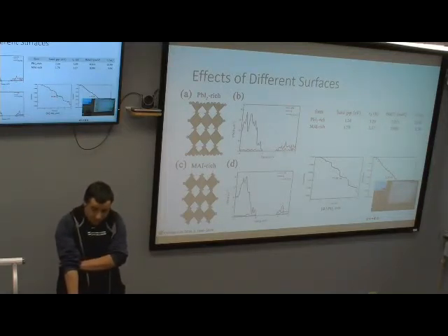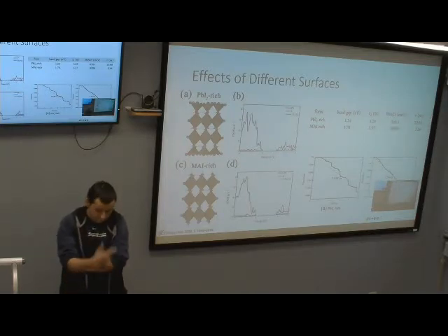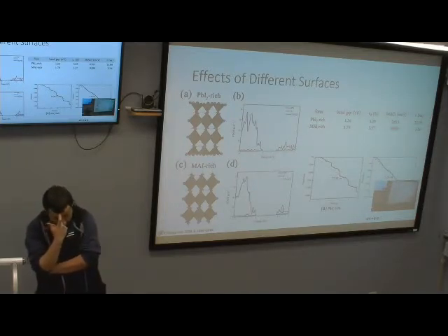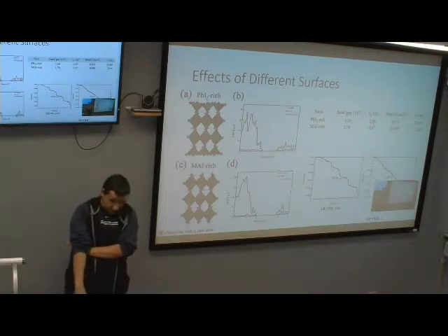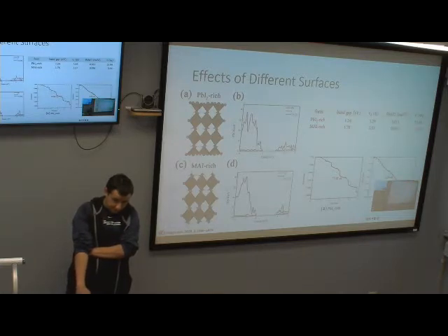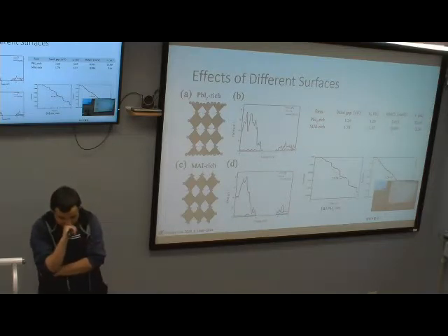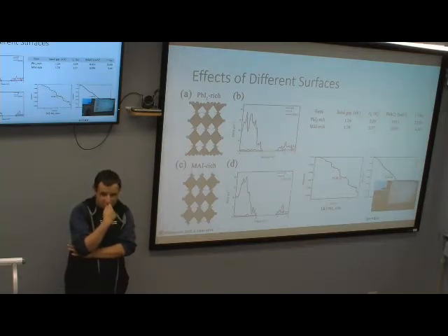If you replace the word energy with probability or chance for longer time, everything will be replaced. So if the non-radiative process is extremely long, it means the lifetime of the excited state is long enough, and during the time before non-radiative recombination happens, there is a higher chance for radiative recombination to happen. And radiative recombination is actually light emitting.